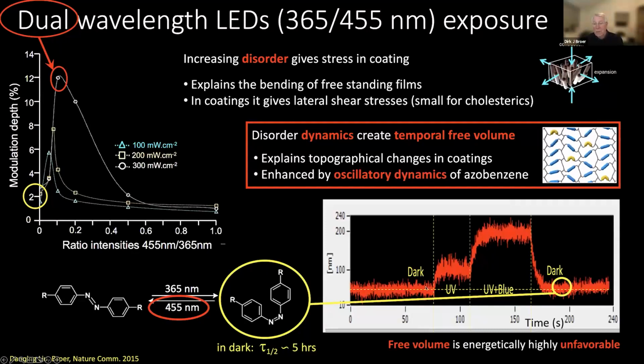So this is basically a thickness measurement of a film. In the dark, you are on this line. If you expose it with UV light, you will have some increase in the thickness. But as soon as you add a little bit of blue light to the system, the thickness of the film increases enormously. And as soon as you switch off the light, within seconds, it goes back to more or less the initial state. But you should remember that in this state, we still have a lot of cis molecules in the system.